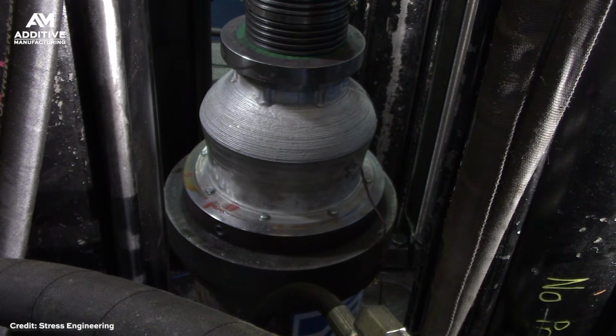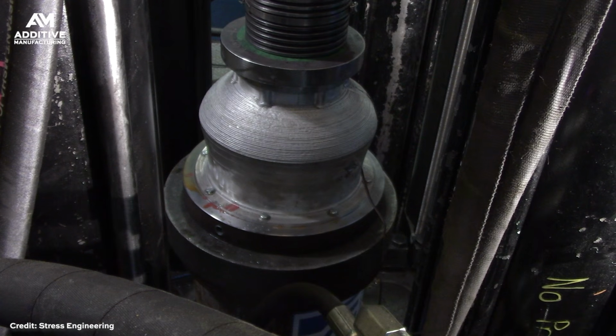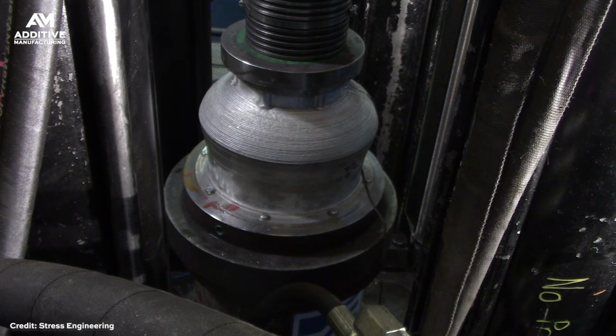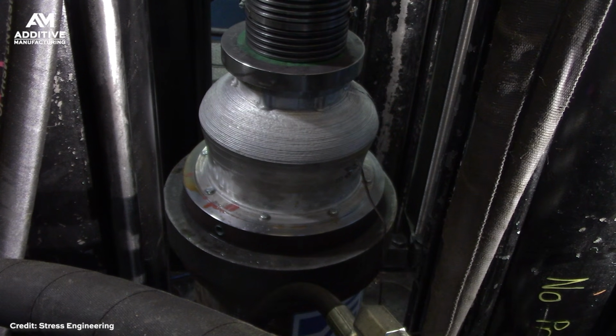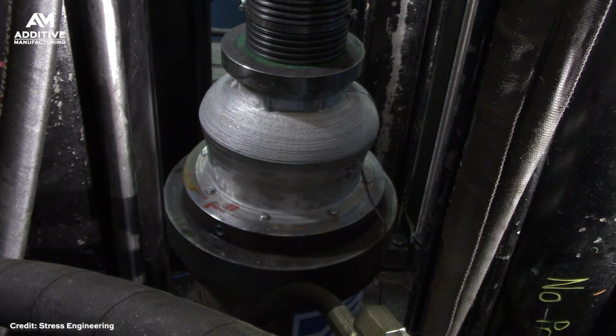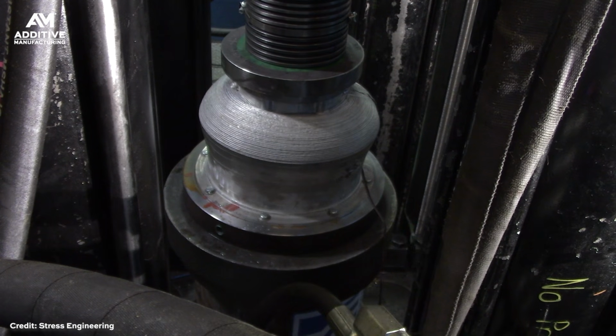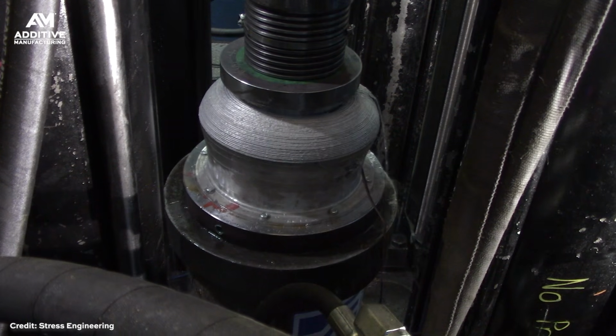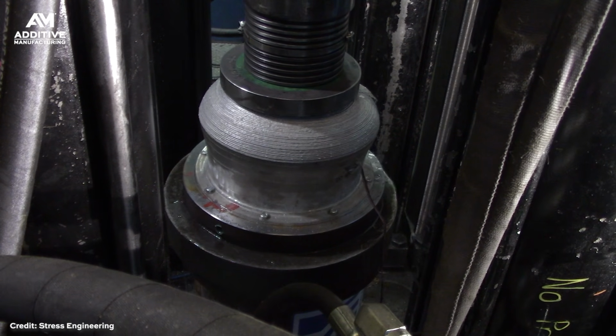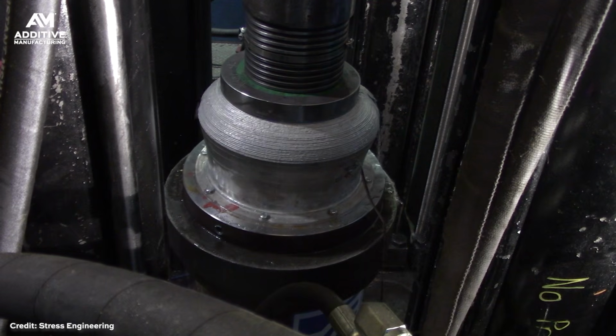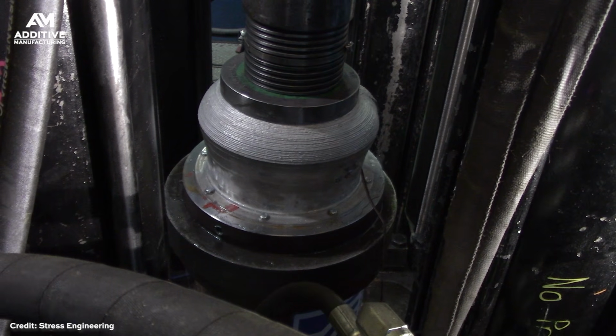internal pressure. After completing that test, our final step was we let the internal pressure stay at 0, and we just applied external compression to the part to see how much compression, just from an axial load standpoint, this additive material would be able to withstand before collapsing. And we were able to apply over 740,000 pounds of force pushing down on this additive part before it dropped load and began to just get squished. 740,000 pounds of compressive force was needed to finally break this pressure vessel.